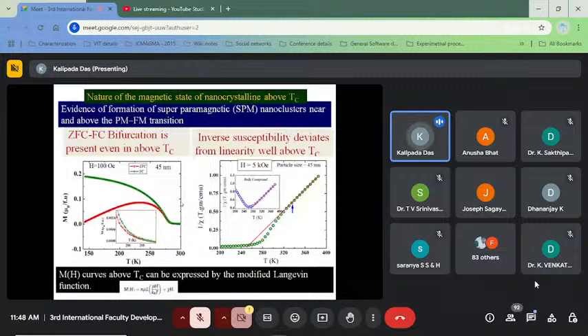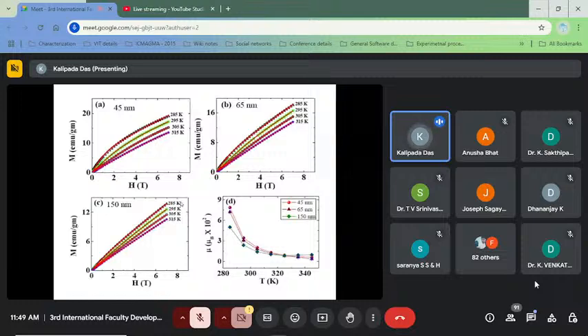So maybe some superparamagnetic nanocluster is present, and to confirm this, we have tried to fit the isothermal magnetization curve by a modified Langevin function, and we see that yes, some ferromagnetic, superparamagnetic nanocluster is there in the paramagnetic state. For the nanoparticle, we estimated the magnetic moment and its variation with respect to temperature, and we see that for the lower particle size nanomaterial samples, it is greater.